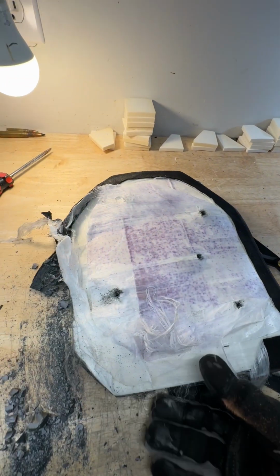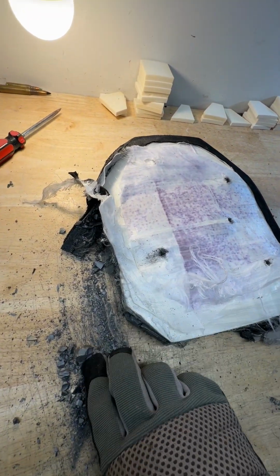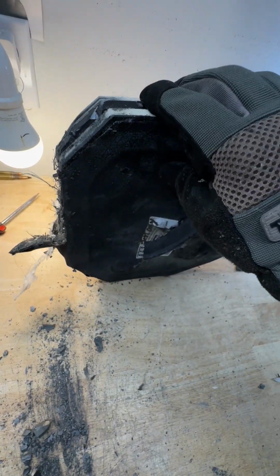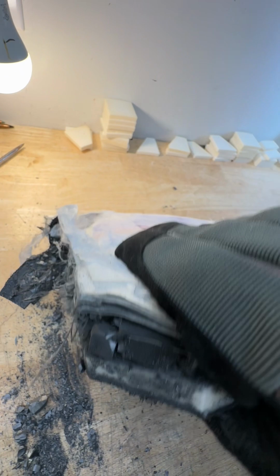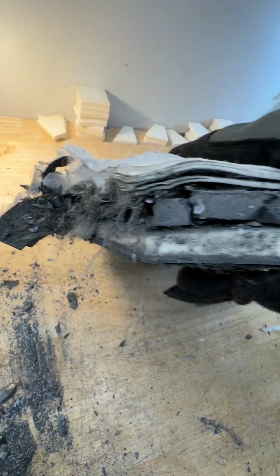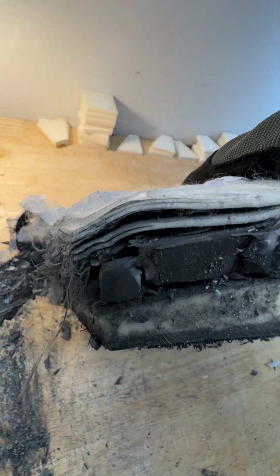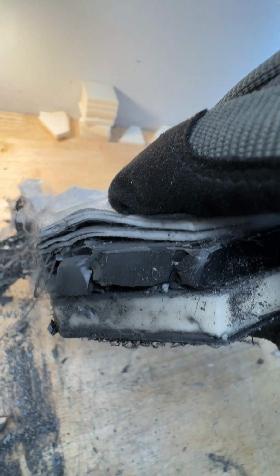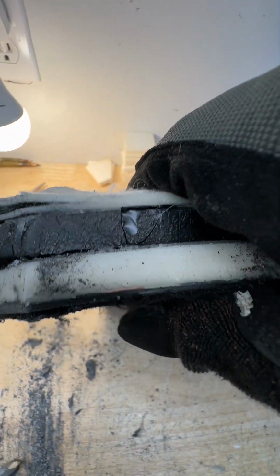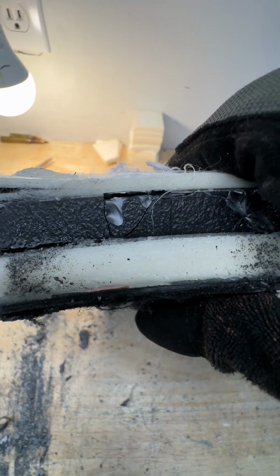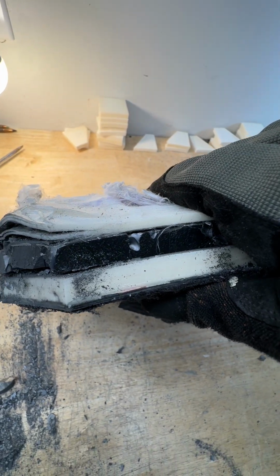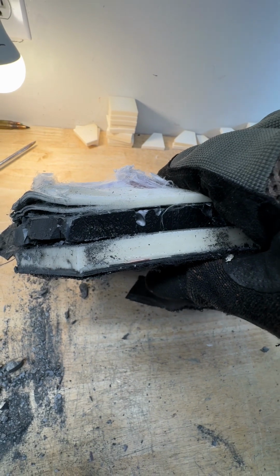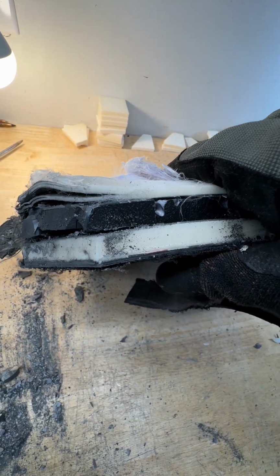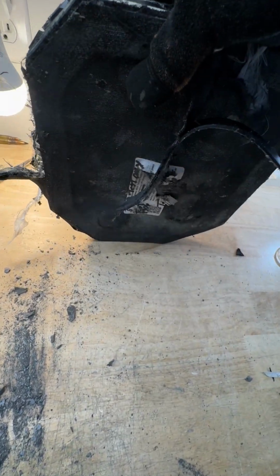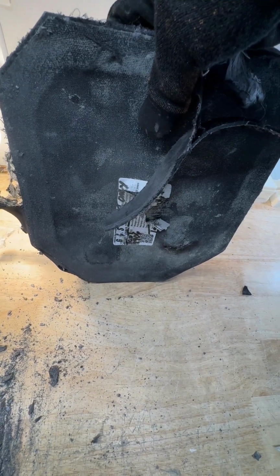All right, so you guys that work with armor know that silicon carbide is a lot sharper. The pieces are a lot sharper. It's a little bit more brittle than aluminum oxide, so you've got to be careful with this silicon carbide when you're tearing the plates apart. But you can see the various layers in the plate, just removing the side fabric, and you can see that there's a trauma reducing layer. You've got polyethylene, you've got silicon carbide plate, and then you have the crack arresting layer on top. This is what a well-designed plate looks like, folks, especially on a monolithic. You've got to be very careful to protect the ceramic strike face with something that does not blow out and that will disperse the ballistic energy back through the adhesive layer instead of out of the strike face of the plate. So this is very good performance on a plate that just took 5 rounds of .30 caliber armor piercing.